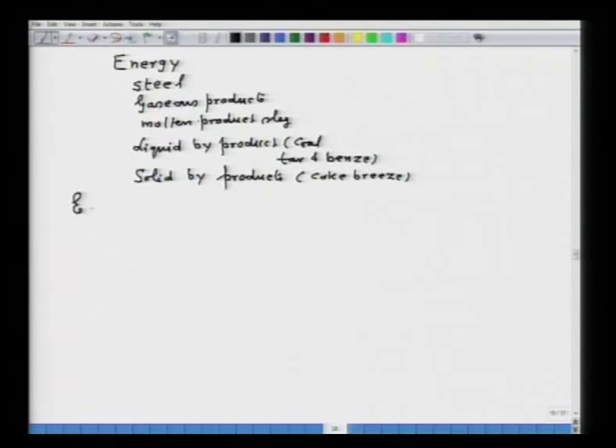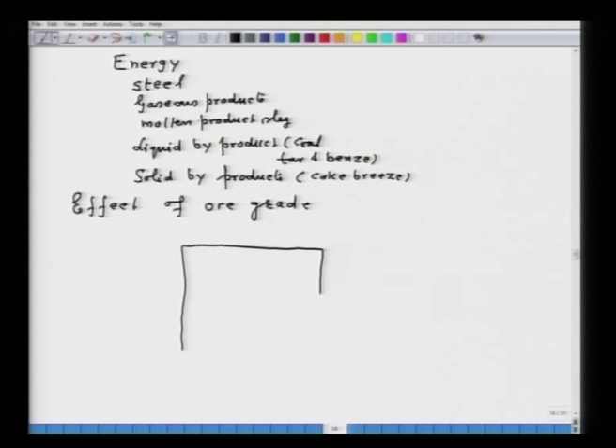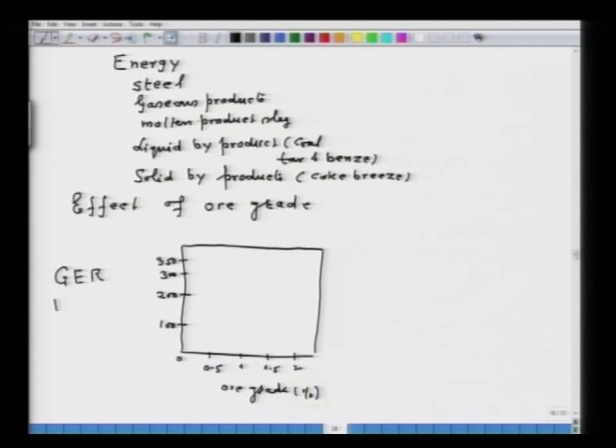Now, let us see the effect of ore grade on gross energy requirement. So, I will again try to plot here. I take, for example, ore grade or metal grade, I will take here 0, 0.5, 1, 1.5 and 2, and here I take 100, 200, 300 and somewhere 350, and that is again gross energy requirement, megajoule per kg. Mind you, now I am plotting as a function of the metal grade of the ore.